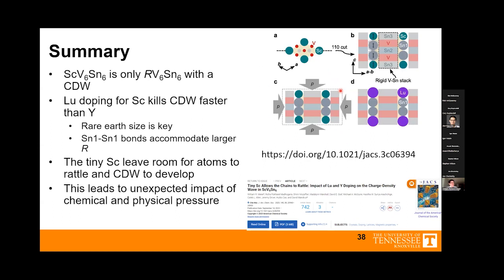So with that, I want to tell you that scandium vanadium tin is special in this vanadium 166 family. It's the only one that appears to have a charge density wave. And if we dope it with lutetium, we see that that charge density wave disappears faster than with yttrium. And that suggests that that rare earth size is key. And we notice from our diffraction measurements that the tin-tin bonds are accommodating that larger atom. And we're squeezing out that extra space between those tin atoms that allowed our charge density wave to develop.